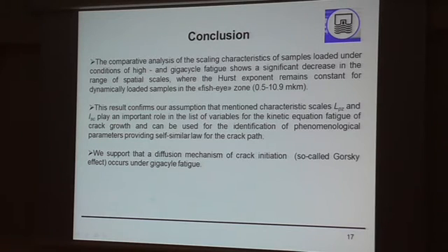And some conclusions. The comparative analysis of the scaling characteristics of samples loaded under conditions of high and gigacycle fatigue shows a significant decrease in the range of spatial scales where the Hurst exponent remains constant for dynamically loaded samples in the fisheye zone.